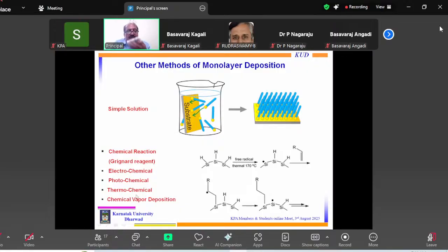A little advanced level is chemical vapor deposition, which is not a very simple one, and you need to have facilities to do so. How does this happen? This is the case of silicon. If you take silicon, what is shown is a hydrated silicon surface. With just a chemical treatment, you can create hydrogen-bonded silicon. Then you can have free radicals, as I said, Grignard reagent, and you can also heat simultaneously to 170 or whatever temperature,